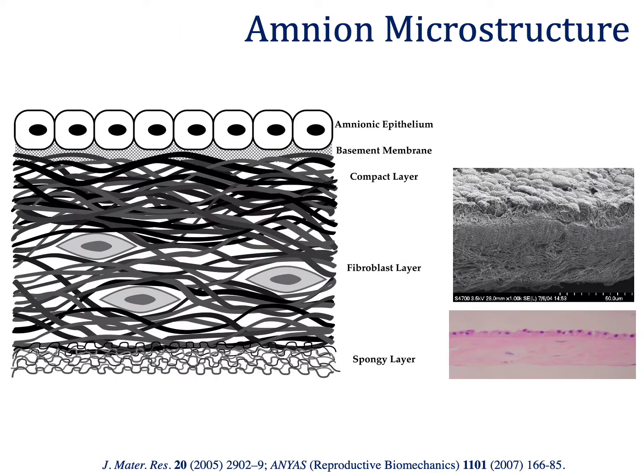So continuing to zoom in on this microstructure, I show the schematic here along with both a scanning electron microscope image on the right as well as a histological image. And what you can see is that this really is a tissue that is primarily made of collagen. There are not very many cells here at all, and what cells there are are mostly on that epithelial surface. There are a few cells scattered within the fibroblast layer, but the compact layer, which is thought to be most important mechanically, is really almost entirely collagen.